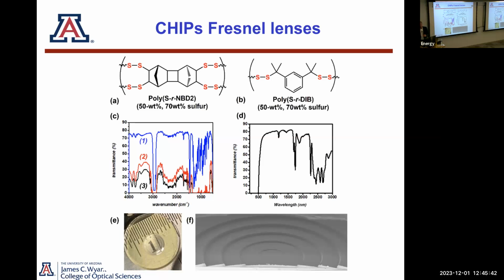In the spirit of some really new results that we've gone forward with these materials, which we call chips, both of these structures are accurate, as far as I know. And this is the structure I showed you before, and this is a different material. We developed this material to be more transparent in the long wave infrared. So you can see the difference organically here: I have an aromatic system here, I have a completely aliphatic system here. Reducing the number of different types of bonds I have helps my infrared transparency. For a long time, the best polymer for infrared optics is polyethylene, because it's very simple. Carbon, hydrogen, that's it. There's no double bonds. It has very strong absorptions at some places like 3.3 microns, but big windows. So that was the spirit here.